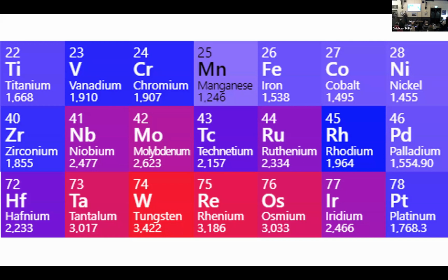And it is basically the only metal that has a high enough melting point and high enough conductivity to take the heat. In this case it's used as a heat sink, so we want it to take the heat away. So it's the only thing that has the conductivity and won't melt, basically. Apart from the fact that we're then introducing all this damage into it, which then changes the thermal conductivity of it. Not only that, we have even more transmutation.